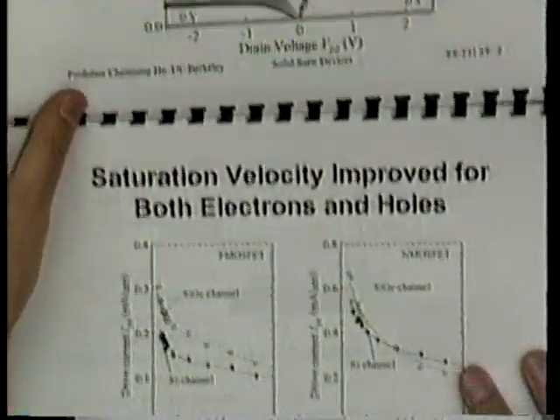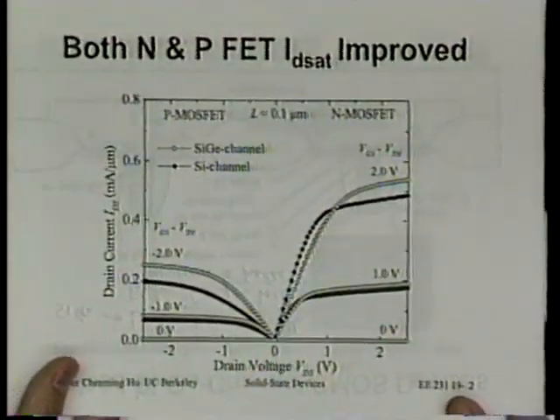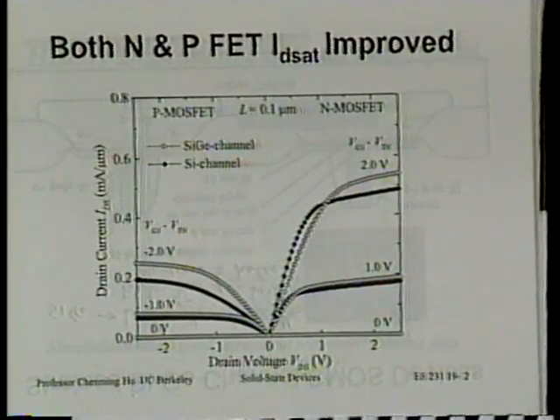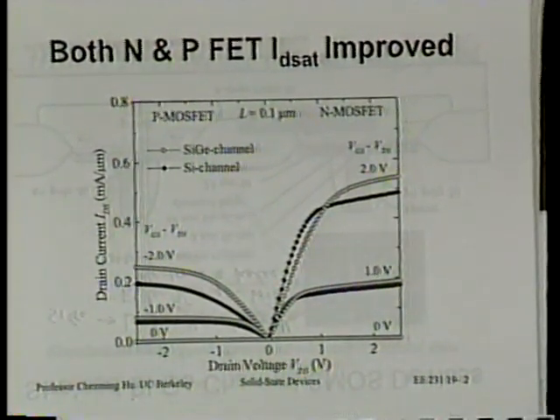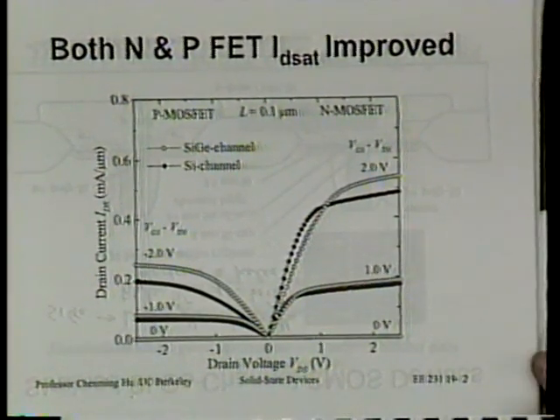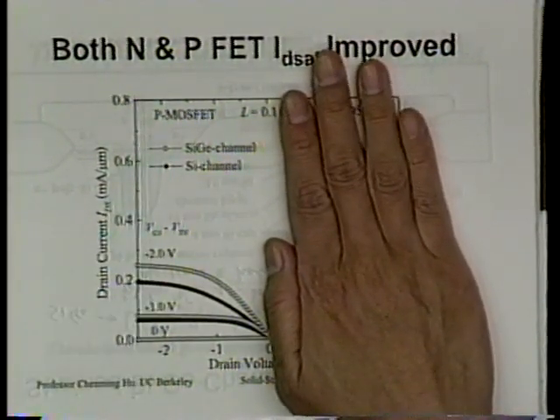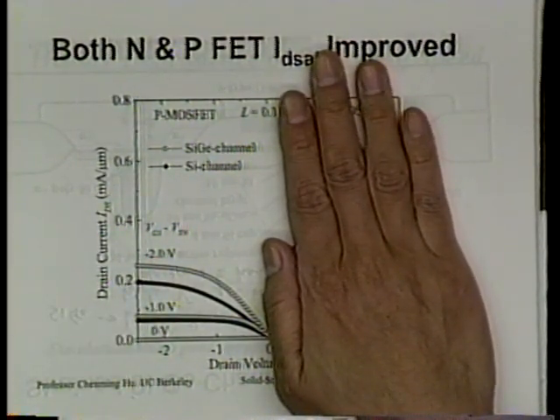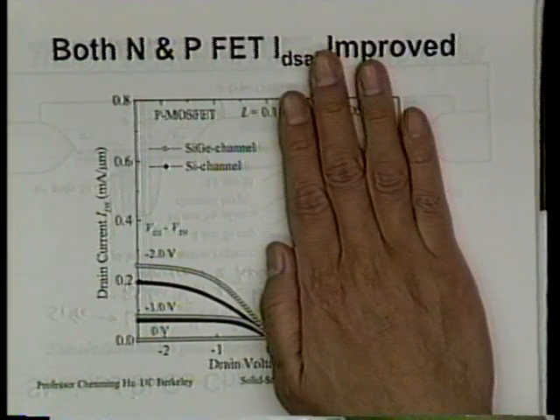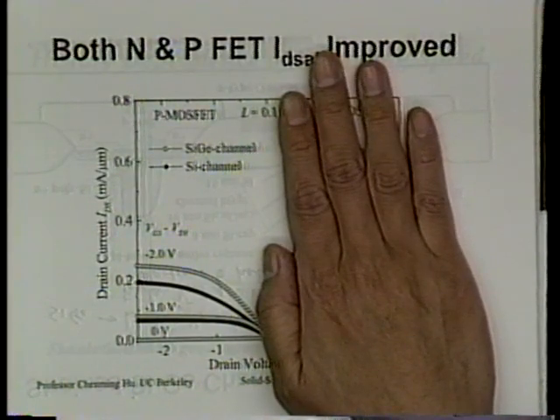So here, I'll show you what we were able to do. Indeed, we did see that both N-channel and P-channel FET IDsat is quite improved. First, let's look at the P-channel side. You notice the open symbol is silicon germanium, and the closed symbol is silicon. The silicon germanium gave us significantly improved IDsat with the same VT. Now this is very significant. This is more than what you can get with one generation of technology scaling, with this much improvement.